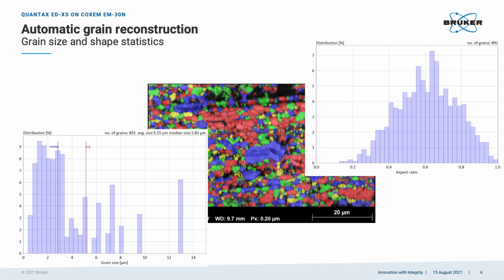And if we then look at statistics, here we have the grain size distribution, where we have a nice peak to the left, let's say for grains smaller than 4 microns, and then some classes of larger grains, and one of them here almost 13 microns in size. And there were 892 grains in this map, and they have an average grain diameter of 5.15 microns.